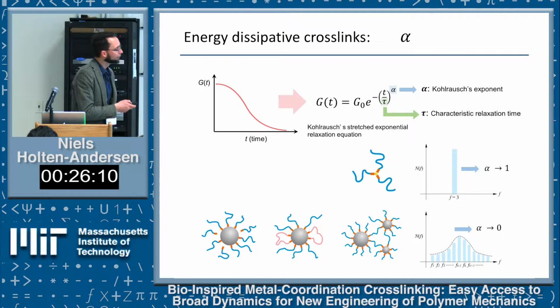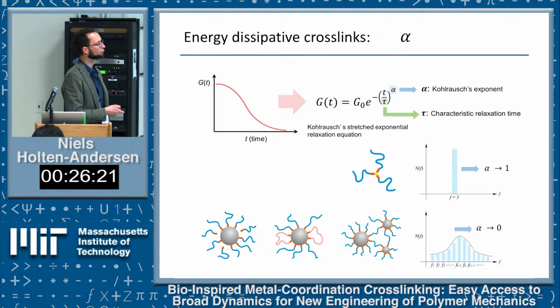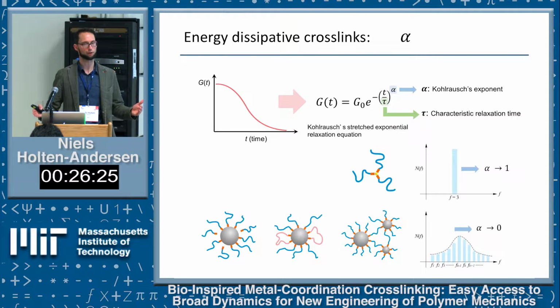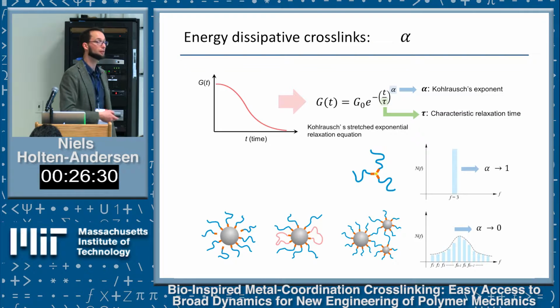We have different ways of crosslinking these networks—we can use metal ions or nanoparticles. In addition to these networks being much more solid-like compared to others, one thing you also get in these more solid-like materials is a much broader distribution of relaxation. The reason we care about that is broader distribution of mechanical relaxation is really the underlying mechanism for toughness.